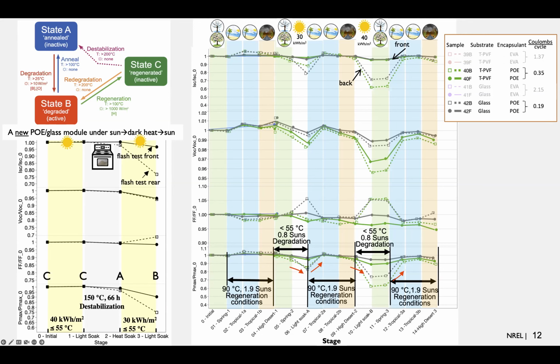So what's going on here, with a view towards this model, is that we're applying, during these tropical and high desert sequences, light up to 1.9 suns and 90 degrees C, the modules reaching 90 degrees C. And during this period, we should be in this state C, regenerated inactive. We are applying light, and according to the models, in order to get degradation, the lights would have to be off.